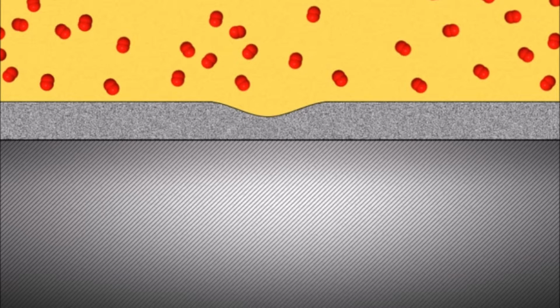"We want an oxide that is liquid-like and crack-resistant," Yang says. It turns out that the old standby coating material, aluminum oxide, can have just that liquid-like flowing behavior, even at room temperature, if it is made into a thin enough layer, about 2 to 3 nanometers, billionths of a meter, thick. "Traditionally, people think that the metal oxide would be brittle and subject to cracking," Yang says, explaining that no one had demonstrated otherwise because it is so difficult to observe the material's behavior under realistic conditions.